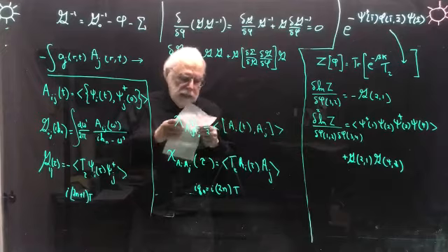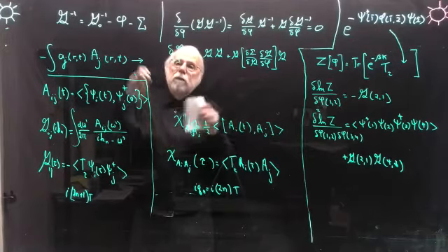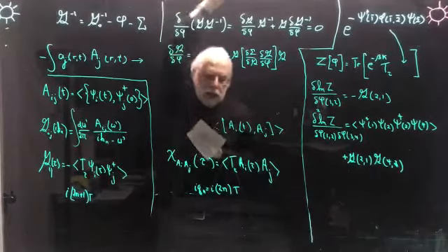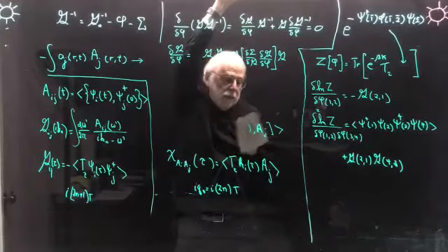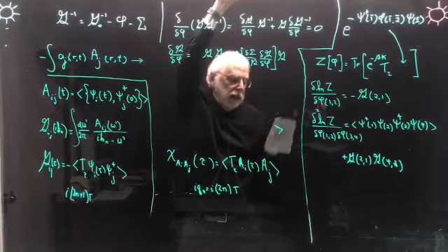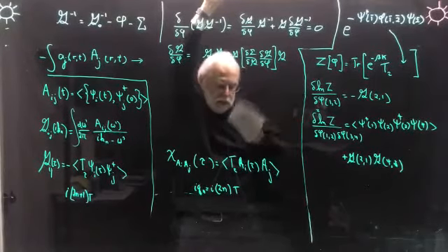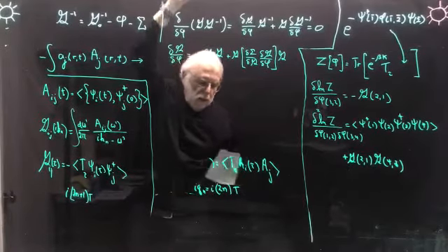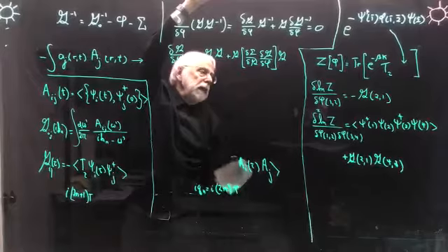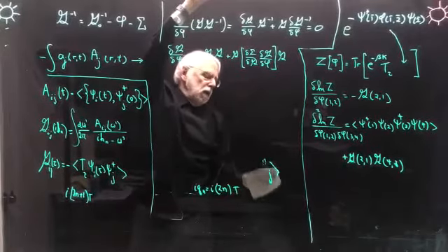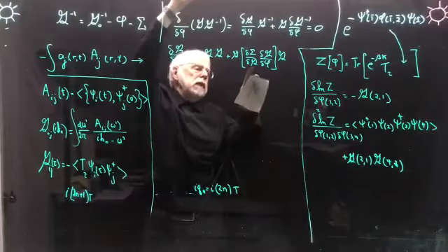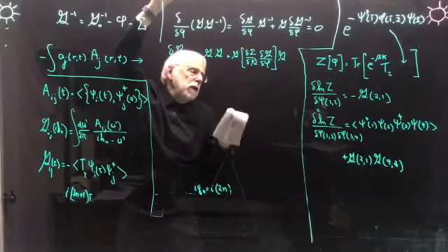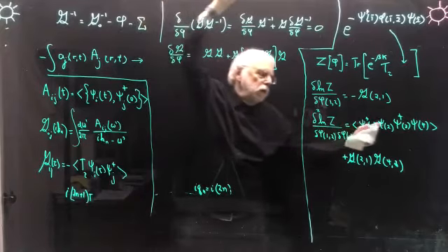So in the interacting case, I have to put the Coulomb interaction to compute the density correlation function, and extract, for example, the dielectric constant that will tell me about screening. So screening is one of the most important things we learn from the electron gas. So how do we get to this? Well, I will do the simplest approximation for this. I will take the Hartree-Fock approximation. So for sigma, I take the Hartree-Fock approximation, which basically amounts to factoring this thing here.